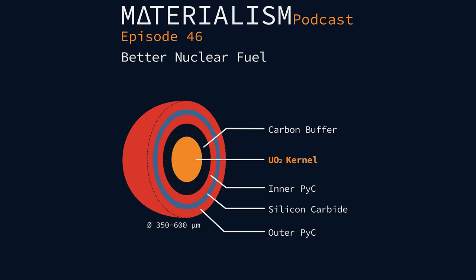Gotcha. And so ideally you want to get the HCl gas out of there, but the silicon carbide that deposits ends up being exactly what you want. And there's a lot of research that's gone into what temperatures you want to process these. Essentially, your goal is to make this as dense as possible. And to do that, you're going to have to keep it above 1500 C. Because if you don't, you can actually get constituent sub-phases that form. And these can be as much as 30% of the total composition, which is not what you want. You want as fully dense as possible. Okay, so if you haven't heard of CVD, it ends up being a really cool process, right?